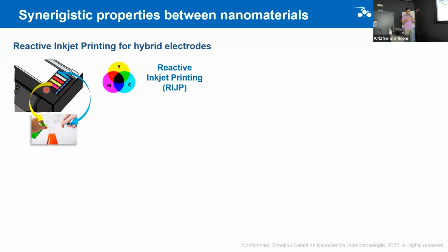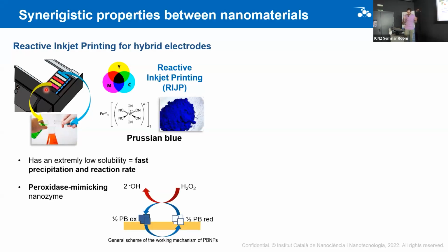We start with one well-studied and well-known example, which is Prussian blue. Prussian blue is a derivative of ferrous cyanide. It's a complex that is basically a metal organic framework, and for biosensing it's extremely interesting because it has peroxidase-mimicking properties. Basically it mimics the action of some natural enzymes, for those who are familiar with HRP. What they do is reduce hydrogen peroxide into water, or actually OH minus.